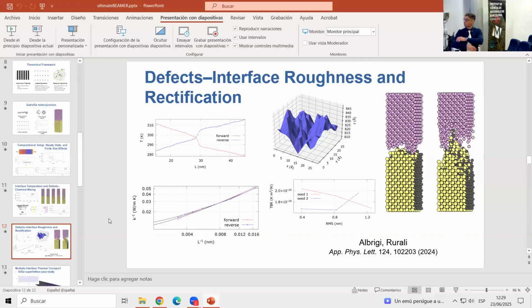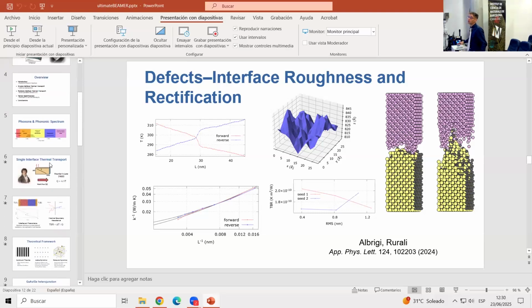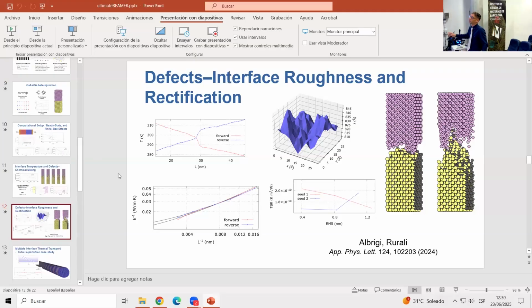I would say that, of course, you would observe a different scenario compared to the one we have found. We would have wanted to see what happens with different materials, but we expected that we would have found some specific trend, because, I don't remember the exact paper, it has been observed in experiments that with increased root mean square roughness, you observe a rather linear increase in the thermal boundary resistance of the heterojunction. We imputed the complete absence of any clear trend in our simulations to the finite size of the computational cross section, and we also thought, from the convergence results at the beginning, that if we repeated the simulations with the cross sections available to us, the results would not have changed much.